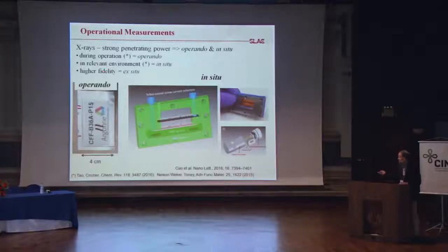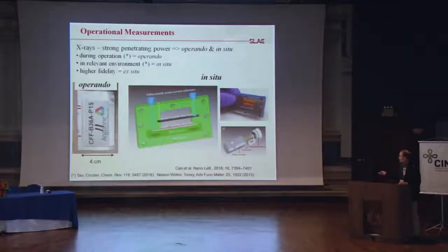And then last, and equally important, is what we call ex situ, where we take this battery, we disassemble it safely in the glove box, and then we'll do a more sophisticated measurement on that. This is useful because some measurements you can't actually do in a liquid environment. Those, from my end, typically involve soft X-rays, anything that involves electrons as well. And I'll show you examples of this. In some cases, this is an extremely important kind of measurement that's necessary to do.